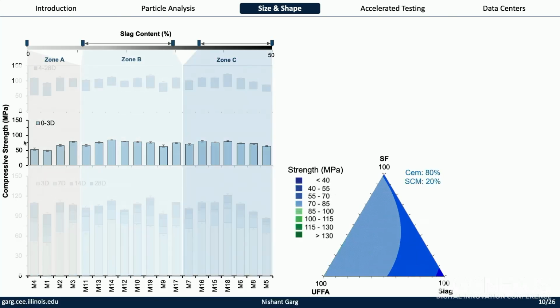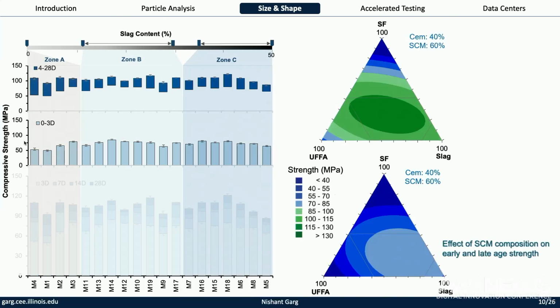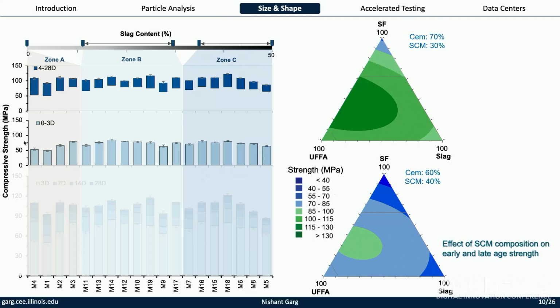Okay. Moving forward, we also take this data for strength. Again, we measure strength at all different ages. We came up with this kind of very interesting charts of how the strength is varying depending on the 3 things here. 3 things here are the silica fume, slag, and ultrafine fly ash. By changing these 3 binders, how the strength changes, we're able to see that.